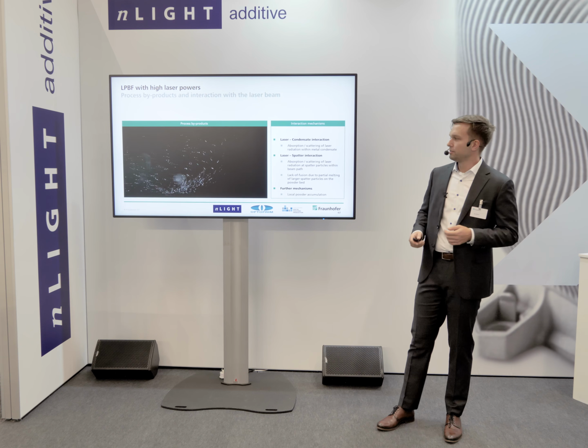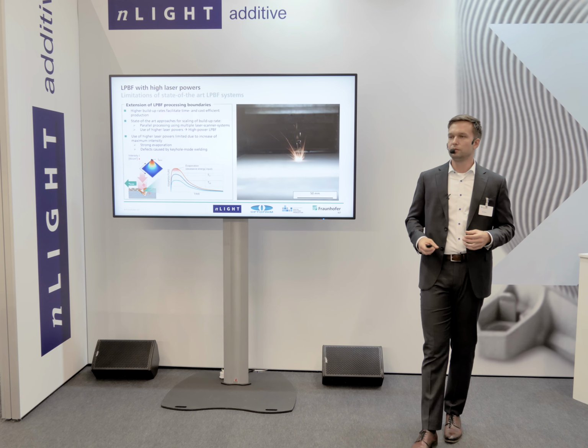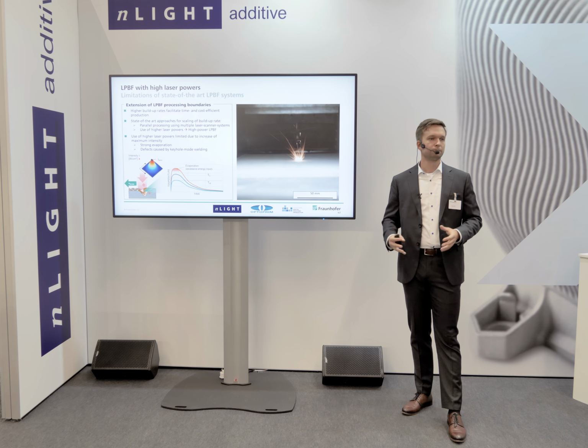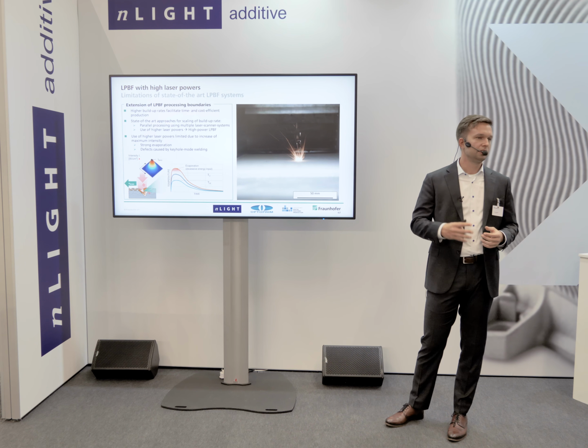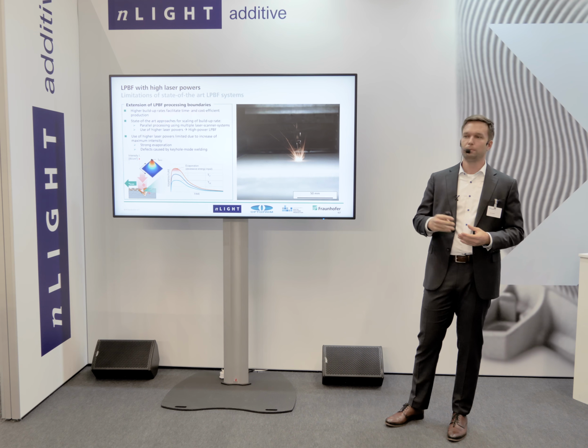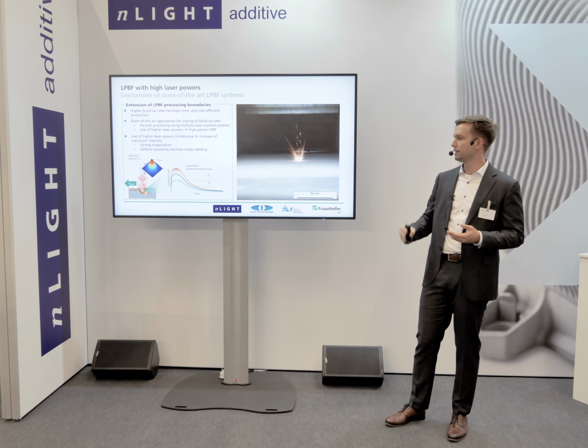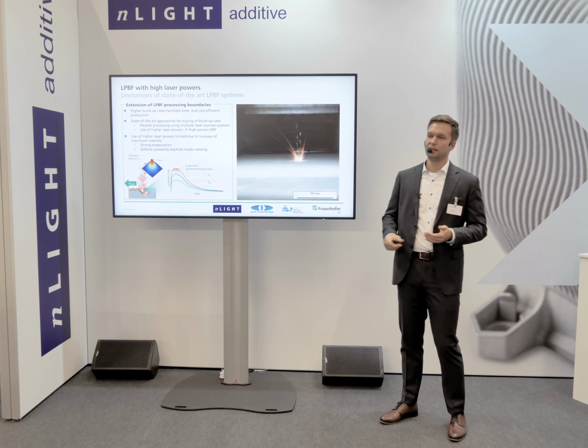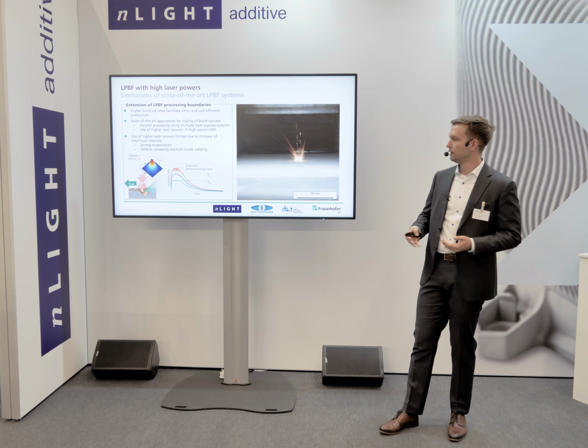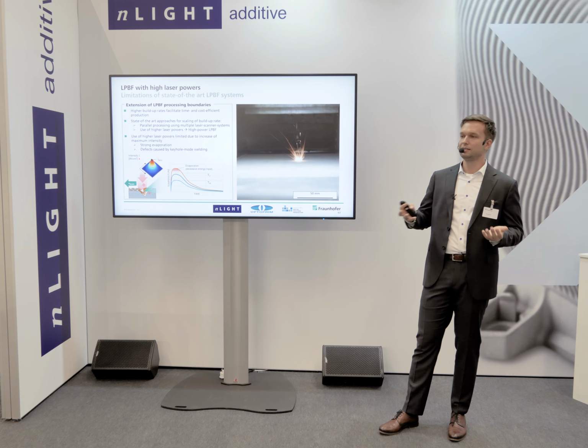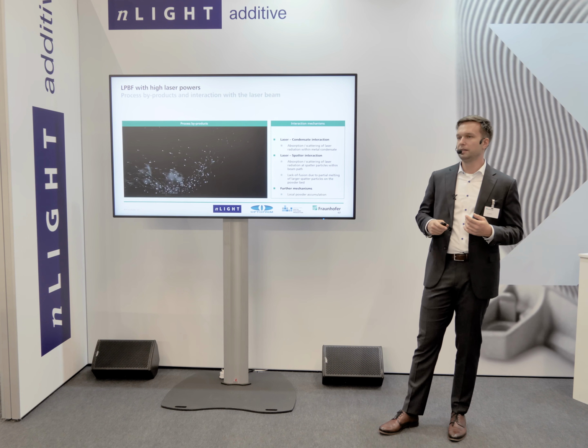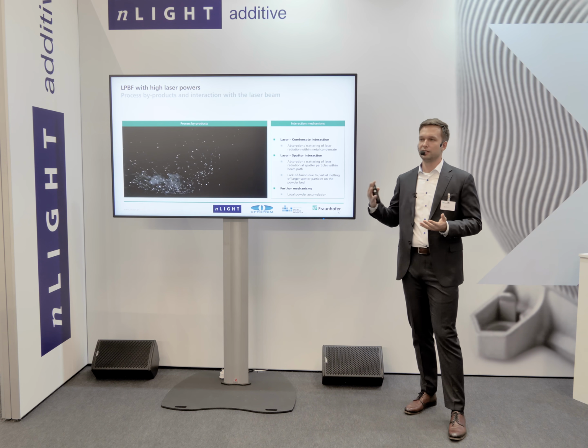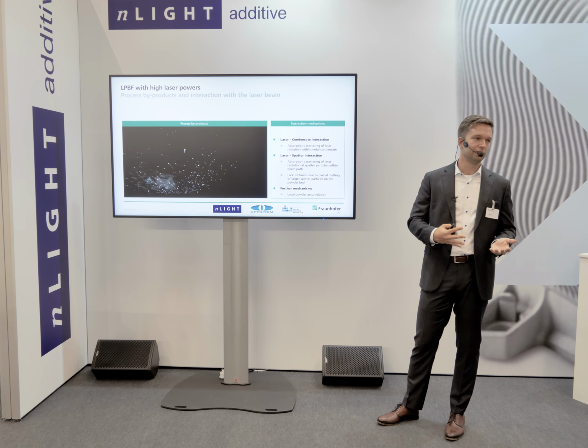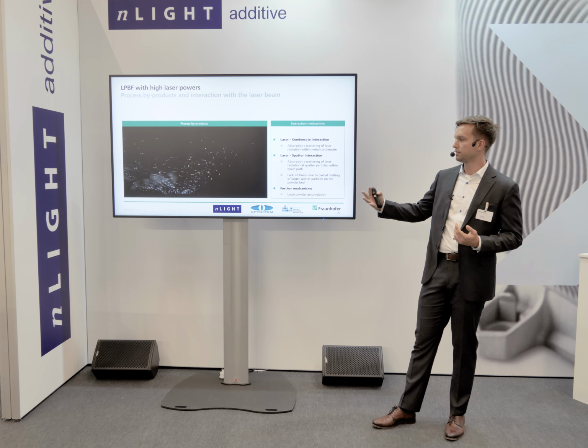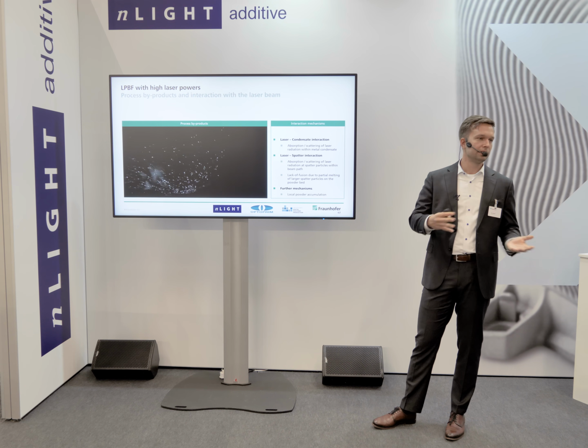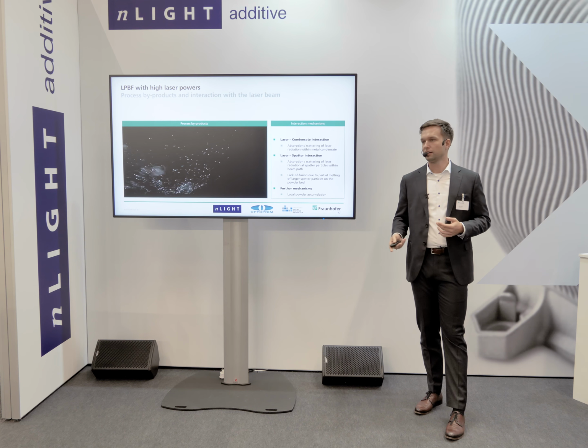And that can be seen on this slide here. When you consider a Gaussian intensity distribution, single mode, at a fixed beam diameter, and you scale the laser power, your maximum intensity in the center will just peak, and at some point the intensity will be so high that you evaporate the material instead of just melting it, which causes a lot of spatter, as you can see in the picture. These byproducts can then interact with the laser beam to cause phenomena such as absorption or scattering of the laser radiation, which reduces the effective energy input, or also defects that stem from the byproducts themselves, because they land on the powder bed and in some regions can cause lack of fusion defects.